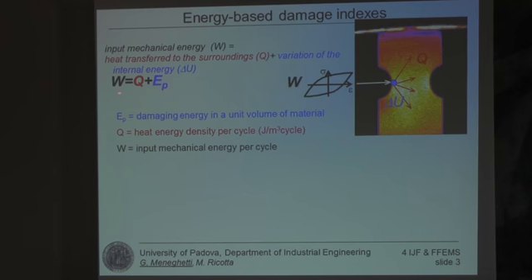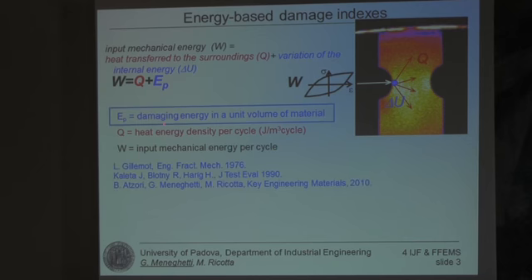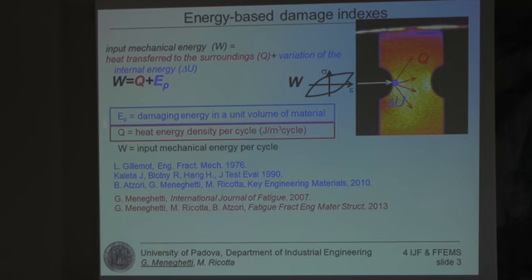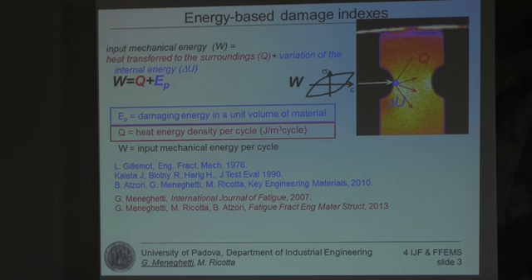That is why researchers in the past brought their attention to the mechanical input energy or to the heat energy density per cycle. So, concerning the damaging energy stored inside the material, which is the true responsible for damage accumulation in a metallic material, we know the papers of Gillemot, Kaleta and Blotny, and also we looked at this energy. Concerning the heat energy, we have proposed to use it as a fatigue damage indicator, even if such energy is not by nature the fatigue damage. It is just an indicator, a useful indicator of fatigue damage. But I will talk about this in a while.